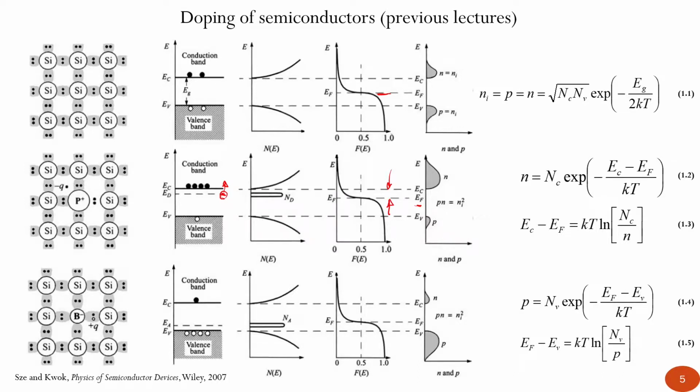So here we have an expression for the equilibrium charge carrier concentration in such a semiconductor, and also, what is important for our further discussion, the depth of the location of the Fermi energy with respect to the bottom of the conduction band. Here we operate with the concentration of charge carriers, electrons, but if all donor centers are ionized, which is commonly the case, we can operate with just the concentration of donors which are provided in the semiconductor.